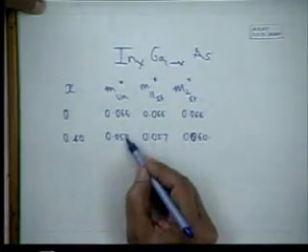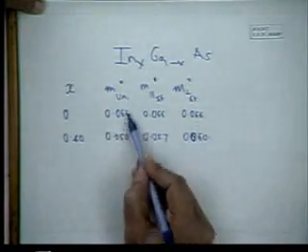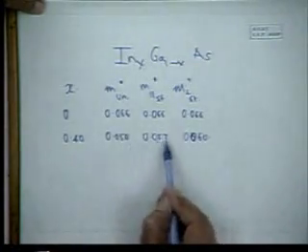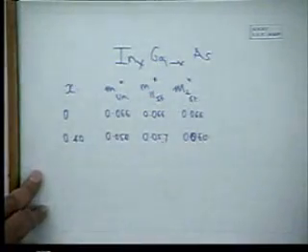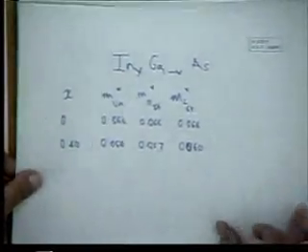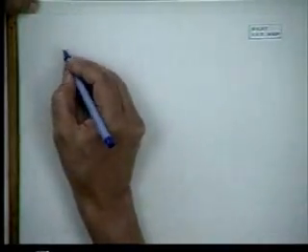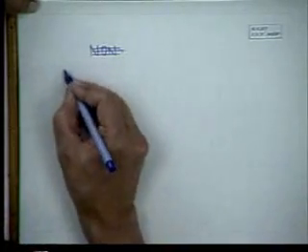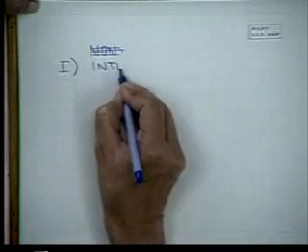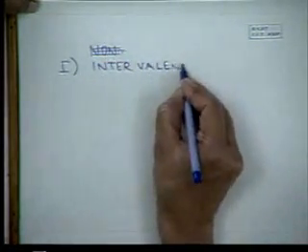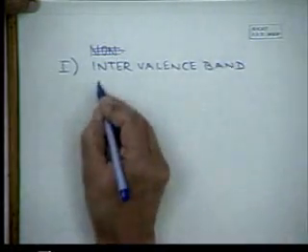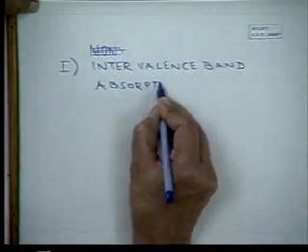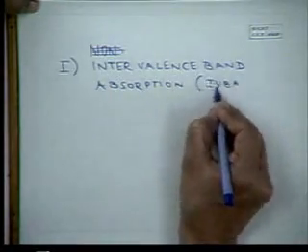So there is more than 30% change due to X, and here there will be about 10% change due to strain. So this is quite significant, and it has to be taken into account. Quite apart from these, the effects of strain is that some of the non-radiative recombination mechanisms, like Auger, are reduced. But one major effect is that intervalence band absorption, called IVBA, is reduced.